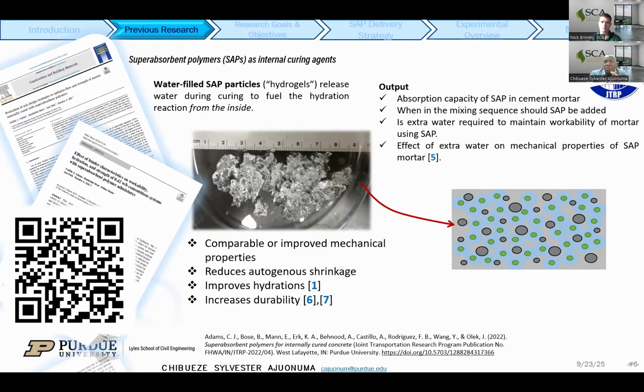Some of the outputs that we were able to generate from there is that we saw comparable and improved mechanical properties of the cementitious mixtures. Also, there was a reduction in autogenous shrinkage, which is key. And then we also found improved hydration, as well as improved durability of the cementitious mixtures.